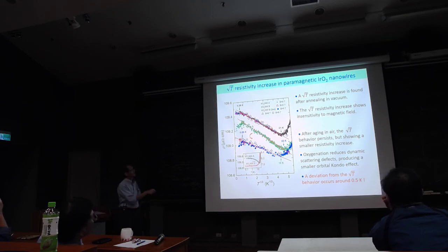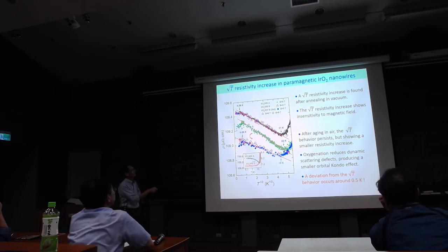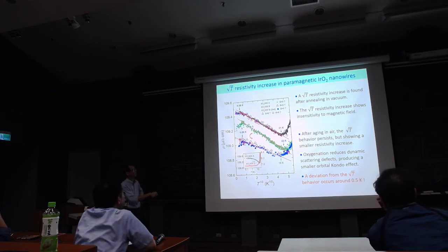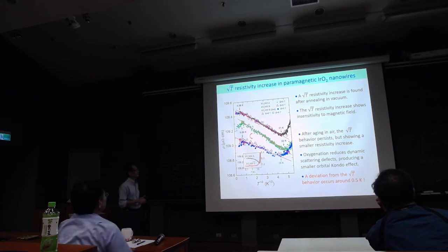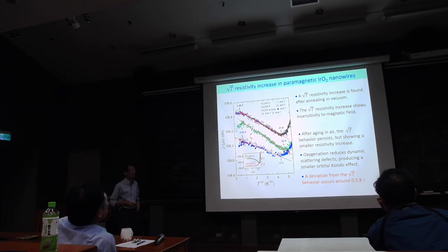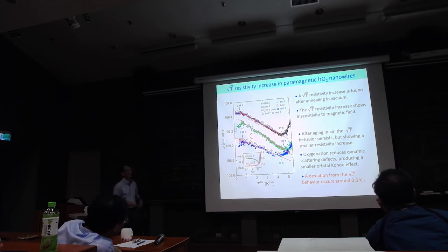You can see that in this case, or in another wire, first, you observe square root T dependence. Second, when you apply magnetic field, there's no change. So there's no magnetic effect or no magnetic moment inside the sample. This must be caused by other origins. And again, here's a different wire. If you put oxygen back, it will go back to this normal resistivity.